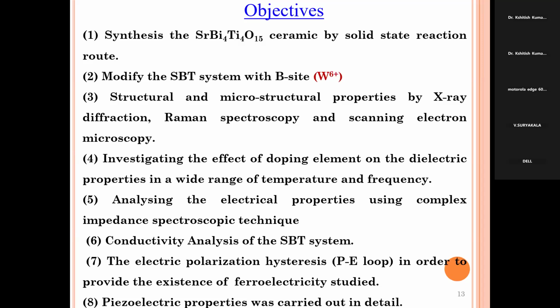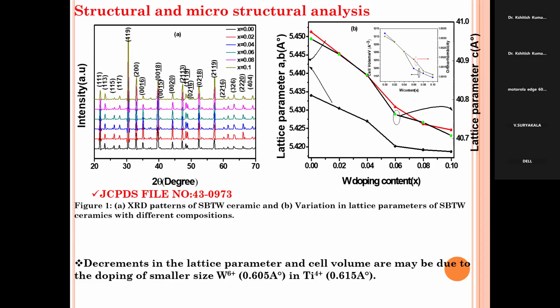How do we confirm whether the material is formed or not? After the calcination, we did the XRD analysis. Let me explain first, then I will explain the XRD result I got. After calcination we took the XRD, and then we mixed the samples again and made pellets, so that we can conduct the electrical characterization.